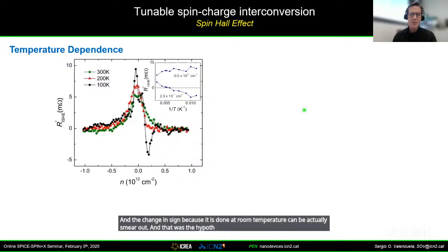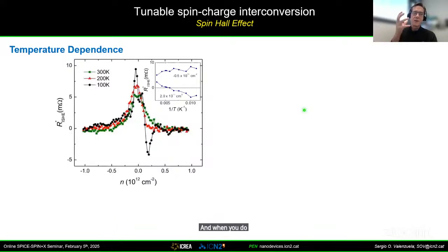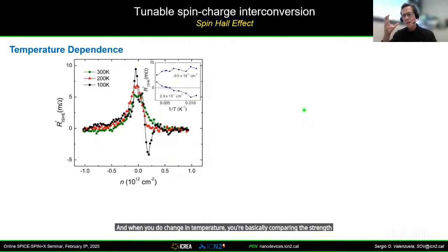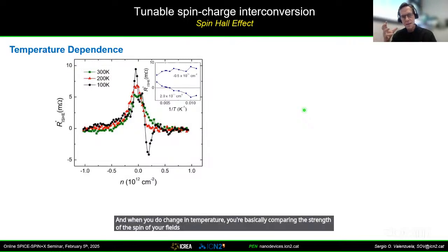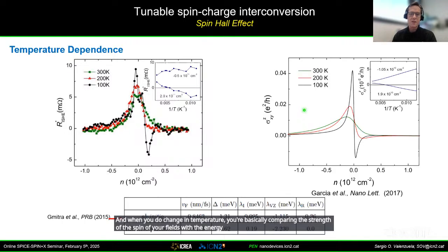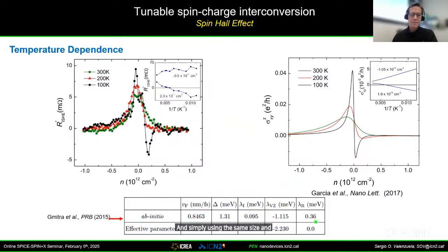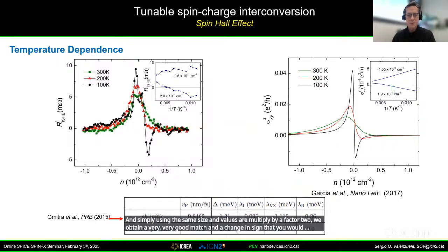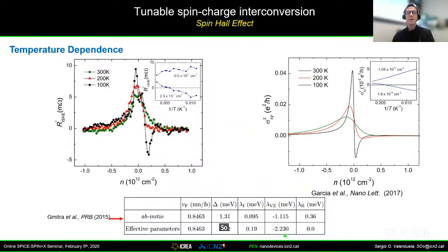So we studied as a function of temperature. And when you change the temperature, you're basically comparing the strength of spin orbit fields with the energy associated to the temperature. And then you can tune the spin orbit fields and find when you find a match. And simply using the same signs and values and multiplying by a factor of 2, we obtain a very, very good match and a change in sign that you would expect. So the valley-Zeeman coupling is of the order of 2 milli-electron volts.